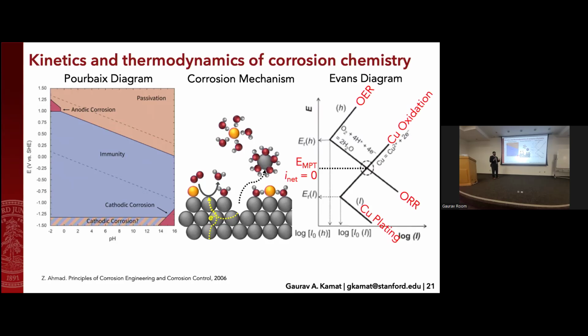And an Evans diagram is what tells us how exactly this happens. So if I look at the intersection of these two lines here, first, this line describes copper oxidation, so copper going to copper ions and 2 electrons. Well, those electrons have to go somewhere. And in this case, if oxygen is available, oxygen reduction on that surface will take them, and you'll form a mixed potential in between both of these equilibrium potentials, but the net current through your electrode is 0, because we're just talking about these local electron flows. As you apply potentials then, you can actually have non-zero net current. So current is either flowing positive or negative through your catalyst that you can measure.